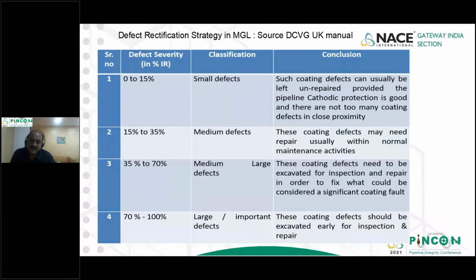Now the defect rectification strategy that we follow is a UK manual for DCVG. As per that, 0 to 15% defect severity are small defects. These defects can be left unrepaired, provided the cathodic protection system is good and there are not too many coating defects in the proximity. Between 15 to 35% are medium defects, and these usually need repair. But we do these repairs whenever we get permission, which is after October and before May, because from the end of May till October permissions for any kind of repairs are not given by the municipalities.